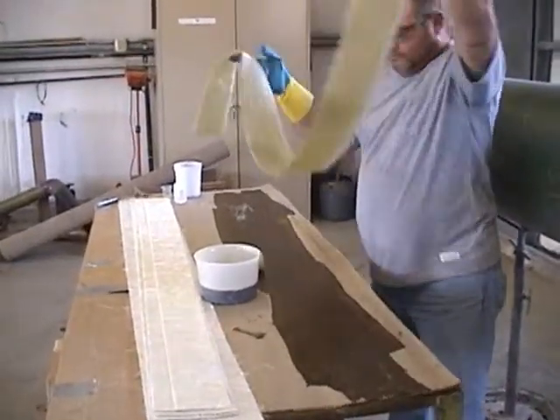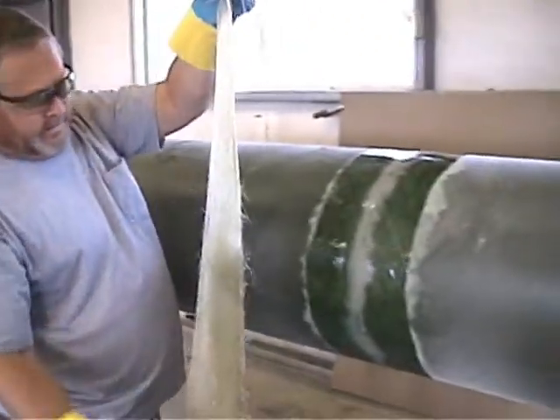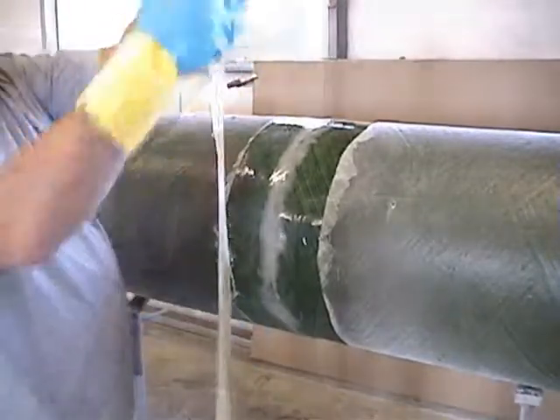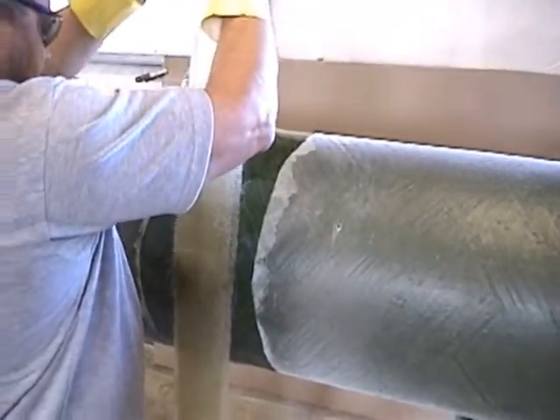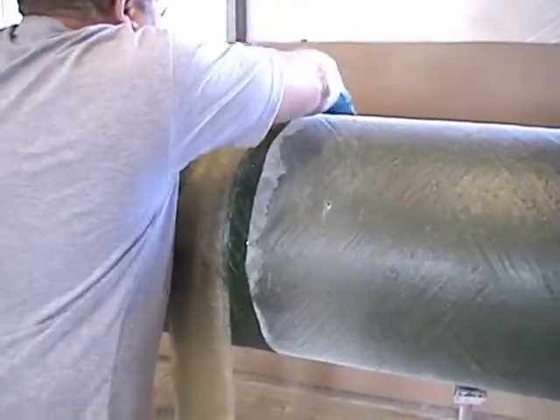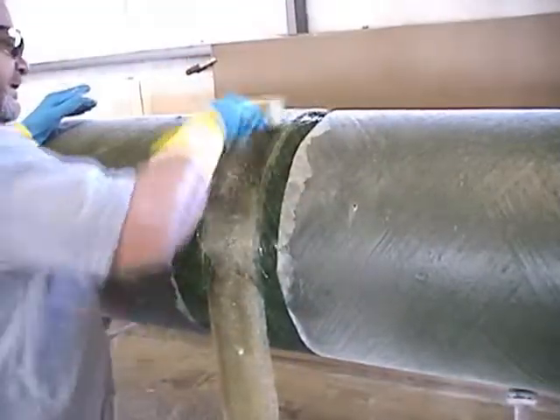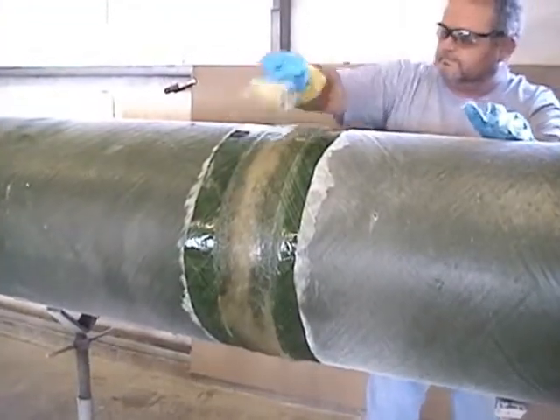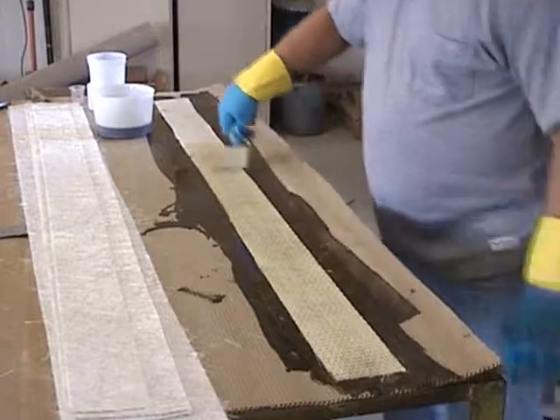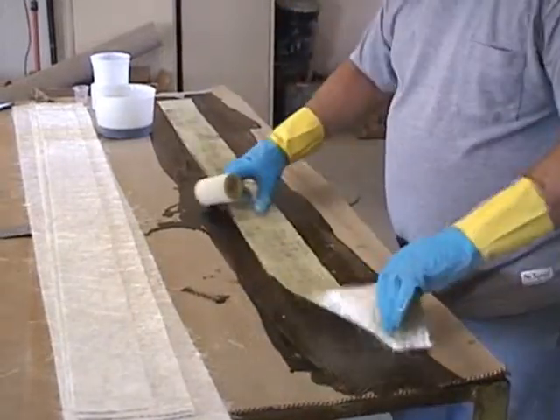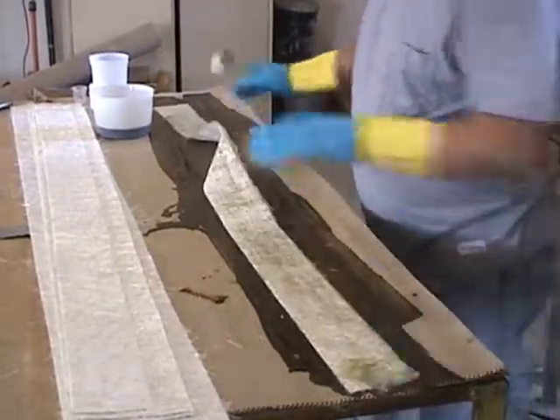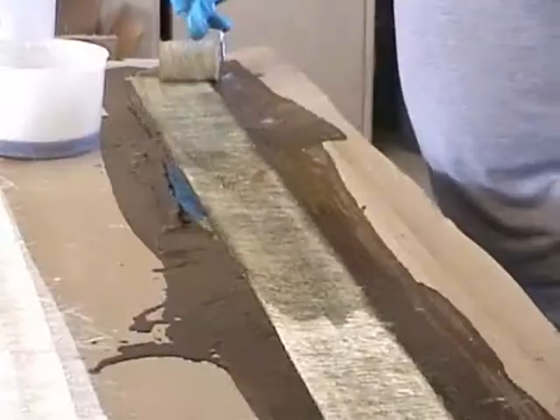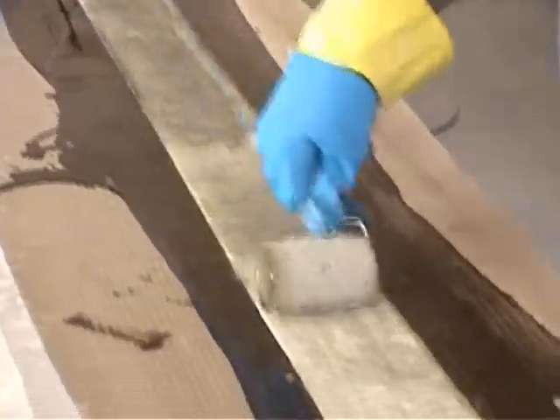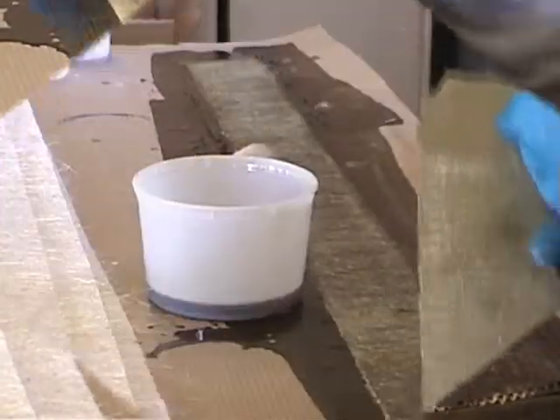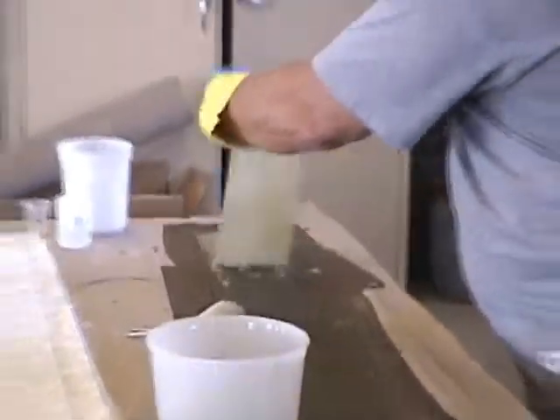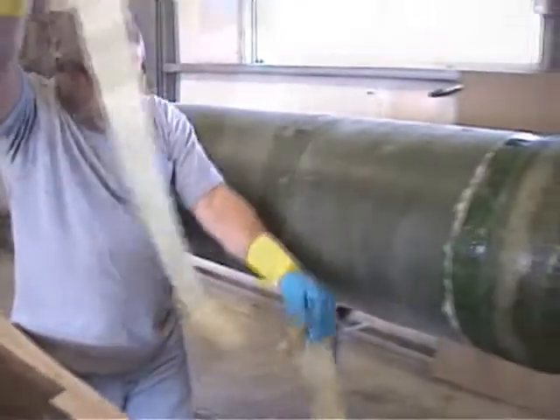Now we have our glass wet out, and we'll apply it to the part with the veil side down against the pipe, laying it right over the center of the seam. Roll it out. Wet the next layer, which is the fab mat layer. We'll wet out the woven side first, then we turn it over and wet out the chopped strand side. Now we'll apply the fab mat layer right over the center.